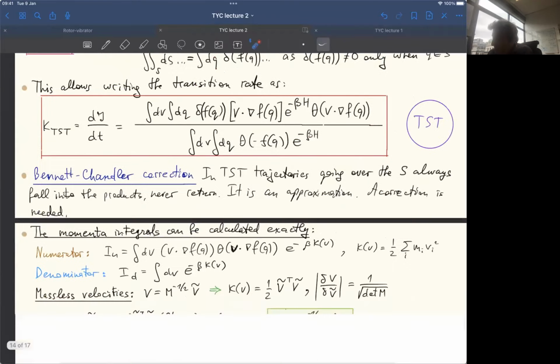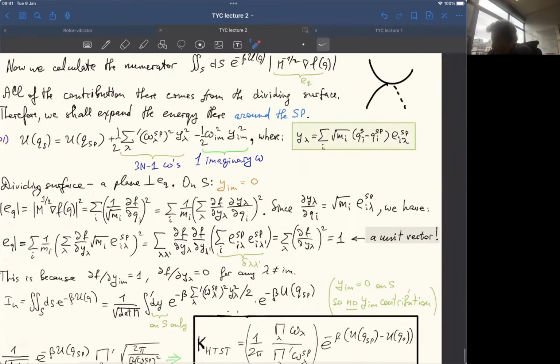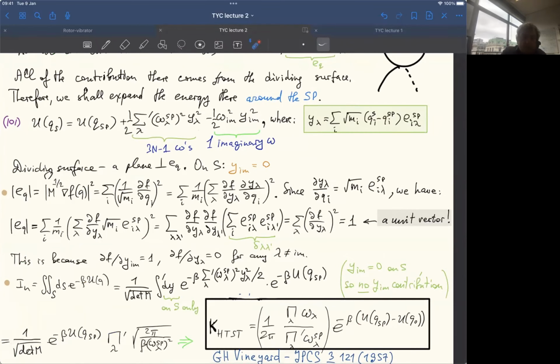So what is the lesson here? If you really want to study kinetics and you would like to study how the system evolves in time, jumping from one potential energy minimum into the other, you will need to calculate these rates. For example, if you're using kinetic Monte Carlo methods, then of course the first thing you would do is to use the nudged elastic band method to calculate the barriers, so to localize the transition state, the saddle point between two minima, and work out the energy barrier.